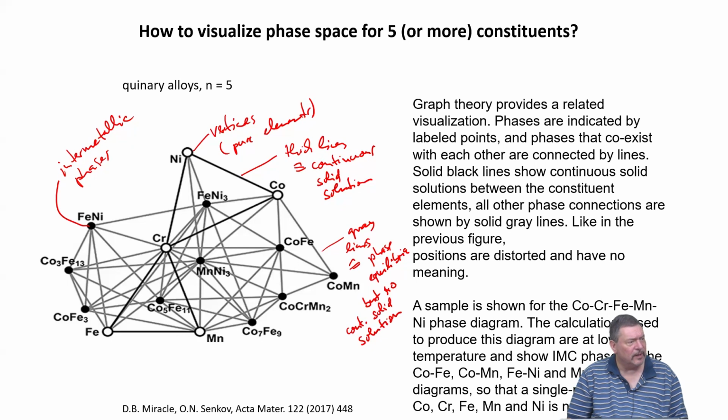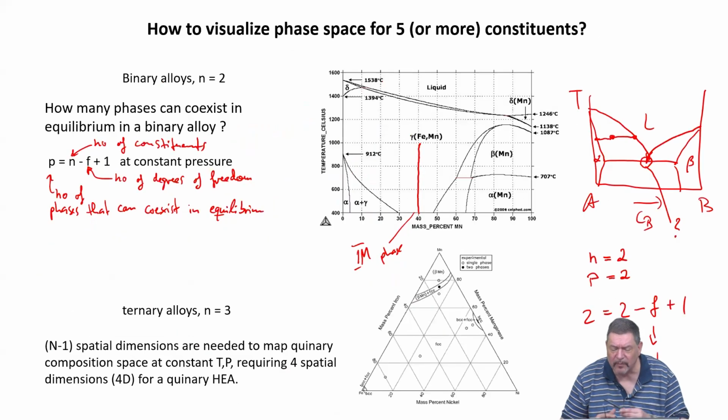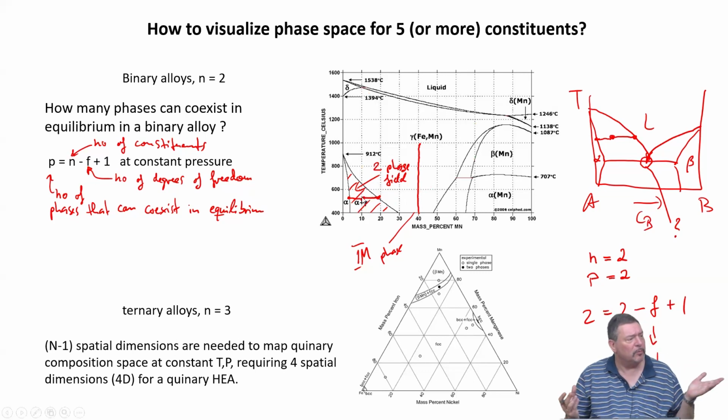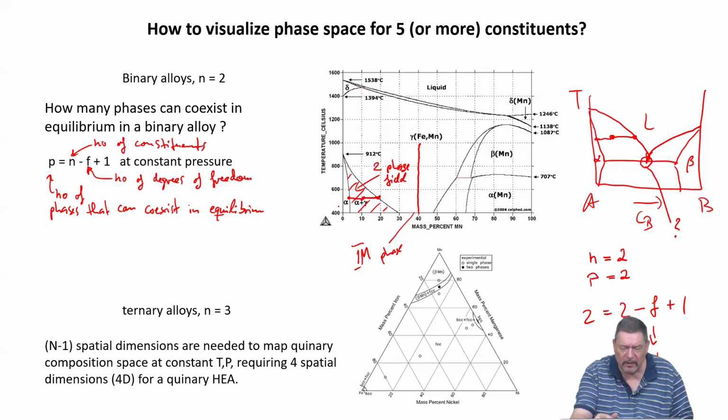The thinner lines are connecting phases again, maybe going to the binary. So you have here a two-phase field. Right, so when you are at any point here, you do a horizontal, which is called a co-node. It connects two phases, this alpha phase here, and then this solid solution phase. Meaning at this point, you have two phases in equilibrium, coexisting. You don't have here in this hashed area a separate phase, you just have the two.